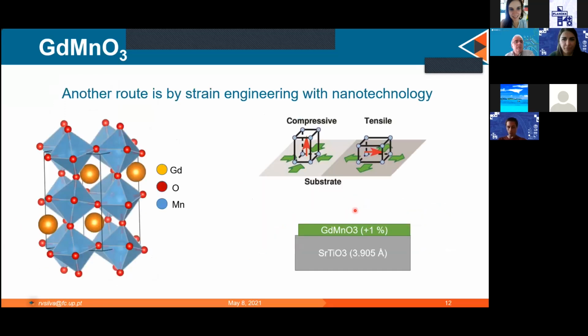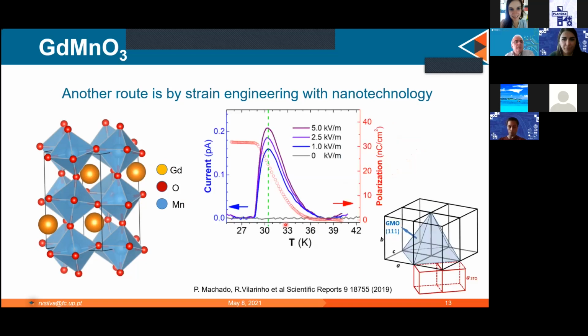Another way to do this without having to substitute material is using nanotechnology. So you can use strain engineering to use a substrate that will change the gadolinium manganite structure in a way that, again, you have the angles that you desire, so that you have that cycloidal, which is ferroelectric. So the way we did this was we deposit the gadolinium manganite on top of strontium titanate. And for very thin films below 30 nanometers, this strain applied at the interface is sufficient that the gadolinium manganite becomes ferroelectric, as it's shown here. It grows on top of the strontium titanate like this figure shows, and then you have a polarization that appears around 35 Kelvin, and then you have a maximum value. So again, you can make another magnetoelectric multiferroic material, not by atomic substitution, but by strain engineering using nanotechnology.